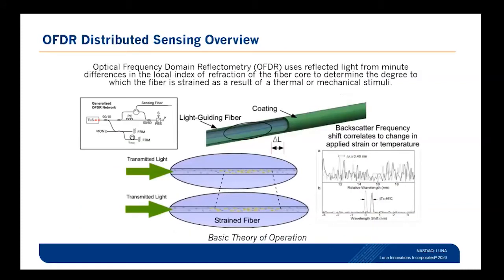And the way that it works is using the principle of the Rayleigh backscatter pattern that's just inherent to optical fiber. So we scan a laser across a preset wavelength range, we send the light down the fiber, and then this weak reflective pattern gets sent back, picked up by our instrument, and using a combination of the time and the frequency domains, we're able to isolate both where along the fiber we're at, and then what order of magnitude something is stimulating the fiber at that point.